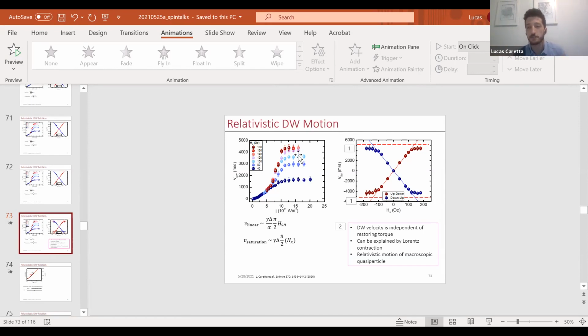Something like gadolinium cobalt: if you take textbook gadolinium cobalt materials parameters, plug them in, and try to calculate the max spin wave velocity, it's something like 25,000 meters per second. So it's much higher. Different materials have different limits. In this particular case of bismuth-doped yttrium iron garnet, this limit happens to be relatively low and accessible for us. I see. Thank you very much for the explanation.